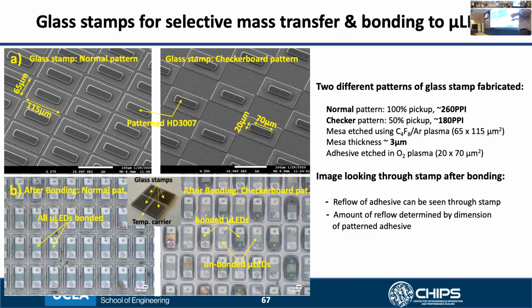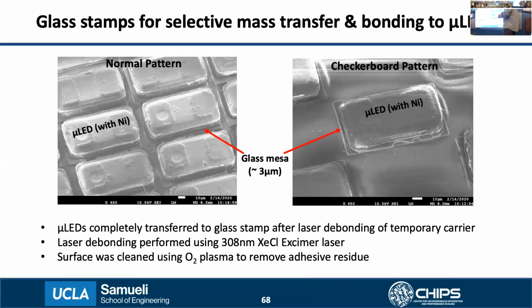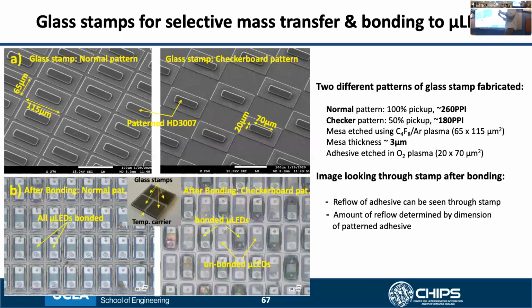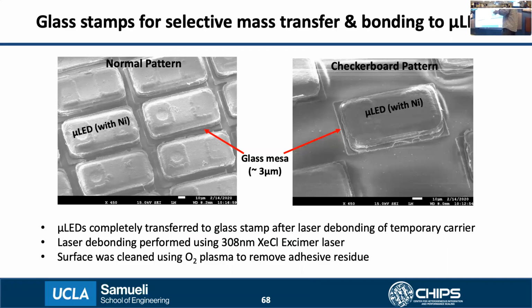On the left side, you see the normal pattern where every LED has been bonded to, and on the right side is a checkerboard pattern of LEDs that have been bonded to. Once this bonding is done, next we do the selective laser debonding using the excimer laser to completely transfer the devices from the temporary carrier onto the glass stamp. And that is what you see in this slide.